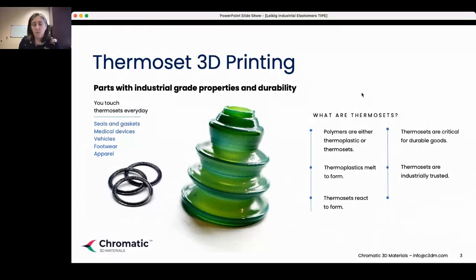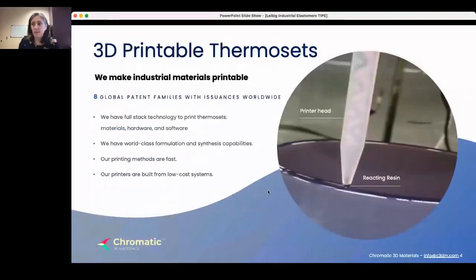So what Chromatic does is we make industrial materials printable. We develop the materials, we develop the printers, and we develop software to enable printing with those materials. And the process we use is like a modified FDM process. Instead of melting, we take two materials and take them through a mix head and that mixing action starts the polymerization. So it's not activated by light, it's just activated by a simple mixing of two materials.